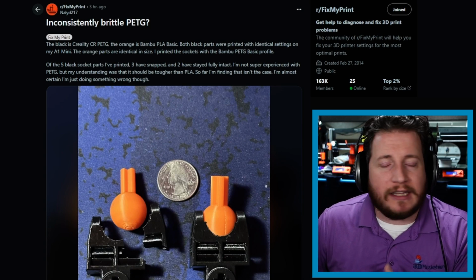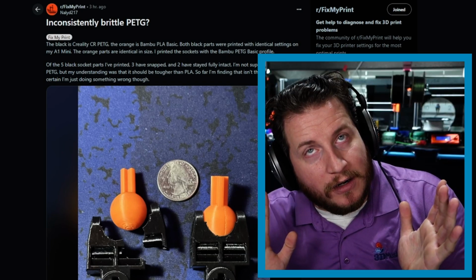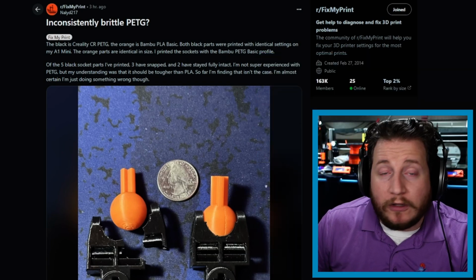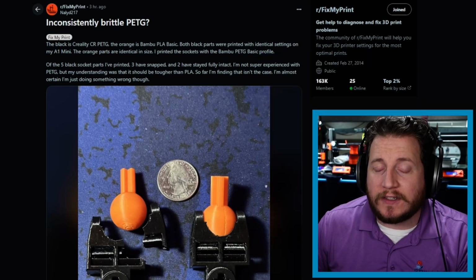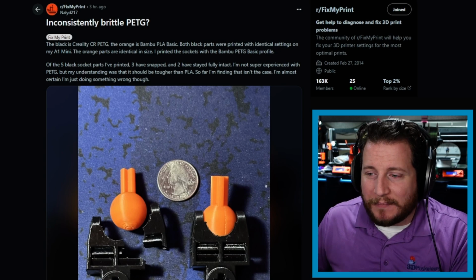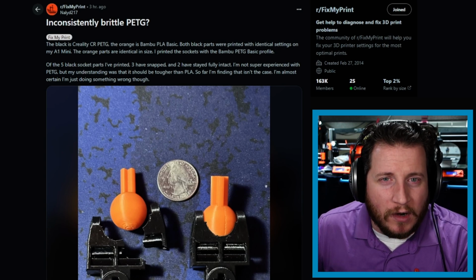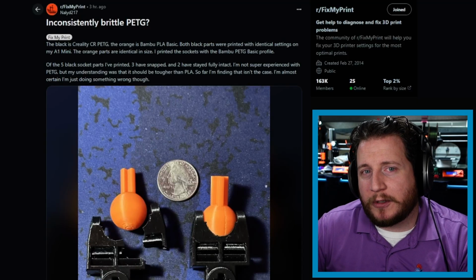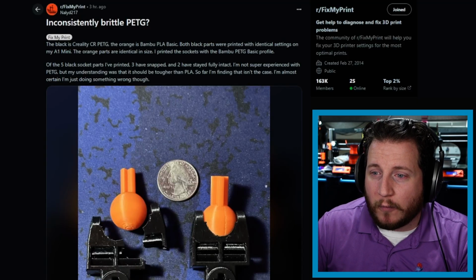With PETG, the hotter you turn it up to a certain amount, the stronger the part will be. You can also look at annealing your parts in post-production to get them to last longer and be a little bit stronger. However, you need to be careful with that, because if you're not properly dealing with those stresses, the parts can warp during that annealing process. So be careful there. That one is a bit of a trap for the young gamers who haven't really gone down the path of annealing just yet. I would say try higher temperatures with the PETG and see if it works.